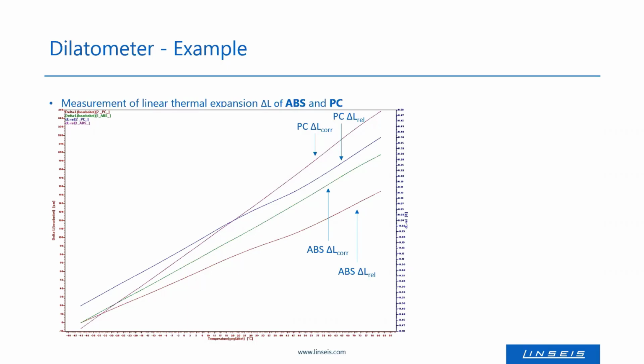So with the dilatometer, one can measure, as mentioned, the thermal expansion, and this can be used, for example, to also find out the right printing properties. For example, if the thermal expansion is really high, it can maybe lead to the material stacking up, and too much material will come out of the nozzle.